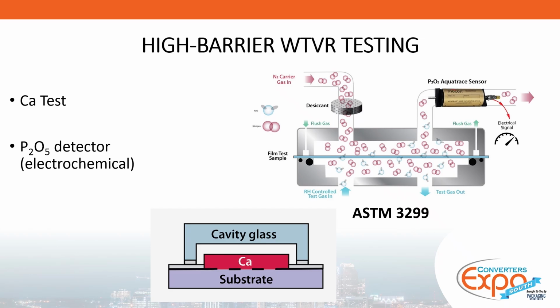So there's really two tests that facilitate very high moisture barrier testing. One very popular, especially for flexible electronics, is the calcium test, to where you actually use calcium as the detector, and you measure the conductance of the calcium hydroxide as the moisture passes through the barrier. It converts into calcium hydroxide, which changes the conductance of the sample. And then you can correlate that slope to a steady state water vapor transmission rate.